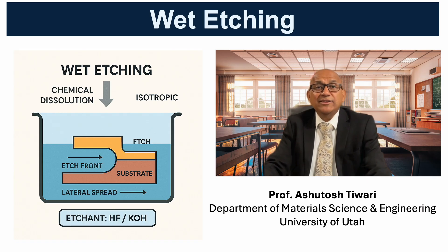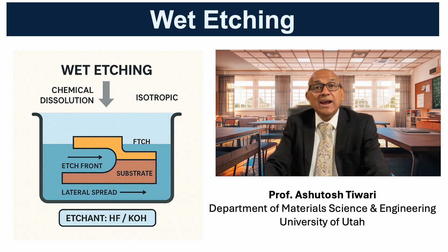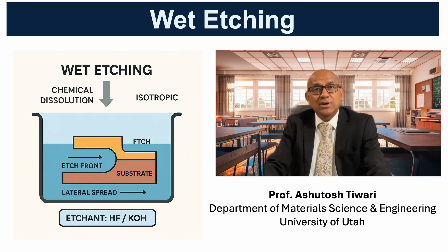Common examples include hydrofluoric acid for SiO₂, KOH or TMAH for silicon, and acid mixtures such as nitric acid or aqua regia for metals. Its limitations are poor directionality and limited control, making it unsuitable for features that require sharp vertical edges.